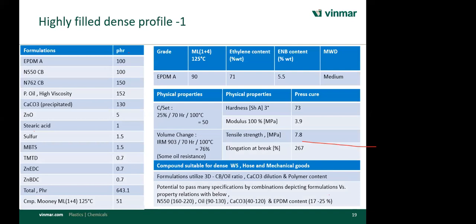So this is the high filled dense profile. If you see the left side, I have shown this is the one EPDM, and you can load as much as 643 phr. This EPDM has a Mooney viscosity, polymer Mooney viscosity 90 at ML 1+4 at 125 degrees centigrade, ethylene content 71, ENB 5.5, and molecular weight distribution medium. Plenty of similar types of EPDM are available in the market. So to overcome the challenges of the supply side, you can increase your filler loading and you can get quite acceptable quantity for physical property.